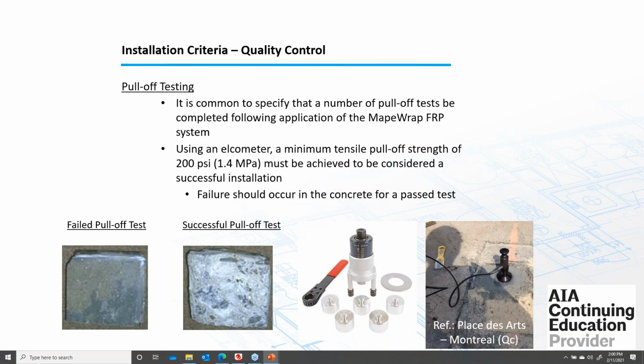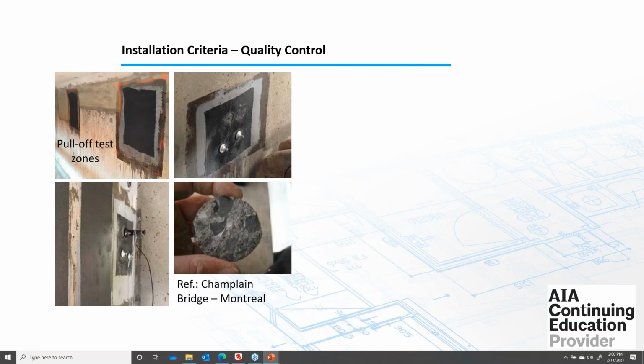For the pull-off testing, a number of pull-off tests can be completed following application of the FRP system. So using the right tool or the right machine, a minimum tensile pull-off strength of 200 psi, 1.4 MPa must be achieved to be considered a successful installation. Failure should occur in the concrete for a pass test. In the next two slides, we will see two different projects where pull-off test was used for bond critical applications.